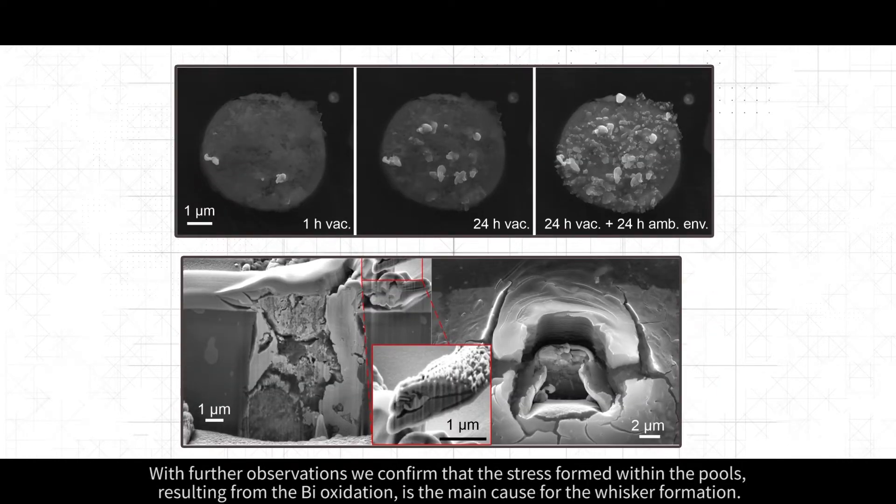With further observations we confirm that the stress formed within the pools, resulting from the bismuth oxidation, is the main cause for the whisker formation.